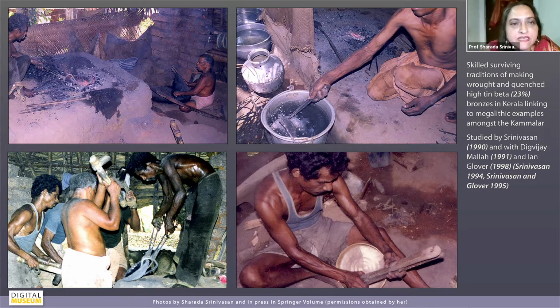So you see that the blank is being annealed on the flame to reach this temperature of 600 degrees, this cast blank of 23% tin. And then they use these very large hammers and alternately kind of forge it in these cycles and all that. And here, in fact, they've stacked several vessels together, so it looks rather thick. But you can see the effort going into it from that kind of thickness to get it down to that extraordinary thinness that we saw.